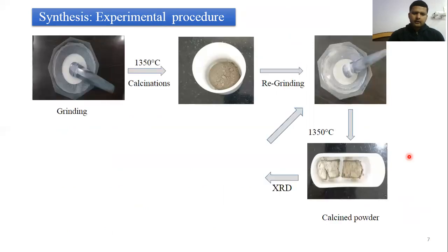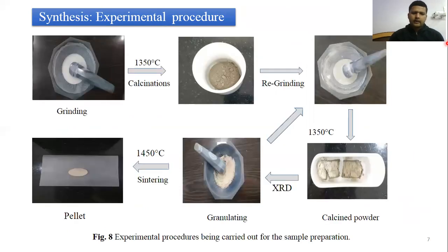The synthesis of the sample was carried out by grinding the raw material for 6 hours, followed by calcination at 1350, and then recalcination and regrinding to confirm the complete phase formation, then granulation, and finally sintering at 1450 or 1500 degrees Celsius for the pellet formation.